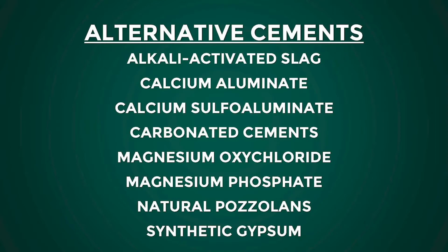They range from alkali-activated slag, which uses ground granulated blast furnace slag, a byproduct of steel production. Calcium sulfoaluminate cement, which uses a significant fraction of gypsum, which can be synthetic and which can reduce the amount of pyroprocessing, or essentially the energy demand when we make the clinker, which is then ground into the cement. Magnesium cements, natural pozzolans. The Federal Highway Administration is investigating natural pozzolans, which are materials that are similar to fly ash. They behave the same. We can replace part of our Portland cement with them, but they occur naturally, and we don't have to rely on coal power plants for these materials.